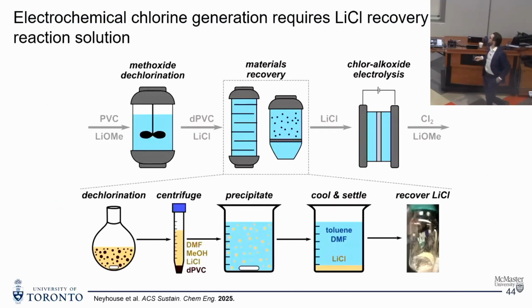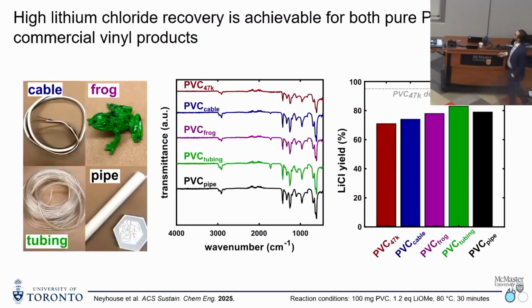So we went through materials recovery, with a few steps to precipitate out the lithium chloride and recover it. We applied this to several commercial products. It's in cable, tubing, PVC pipes. It's in a lot of children's toys, like soft, flexible toys. All of these show very high lithium chloride recoveries, and we were able to take that lithium chloride and apply it in our electrolysis system.